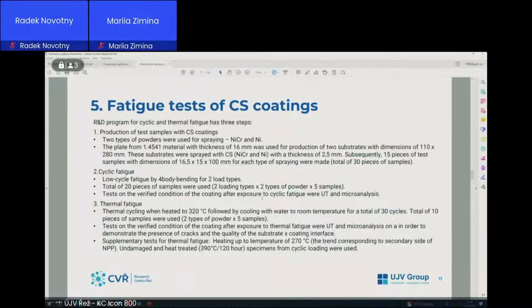This year we performed fatigue tests of cold spray coatings. First we manufactured a plate and sprayed it with nickel chrome and nickel powders. As a substrate we used steel 1.4541 with thickness of 16 millimeters, and then we cut this plate and we received 15 pieces of each. So in total we had 30 pieces of samples. And then we performed cyclic fatigue and thermal fatigue. What concerns cyclic fatigue, we had 2 types of loads.